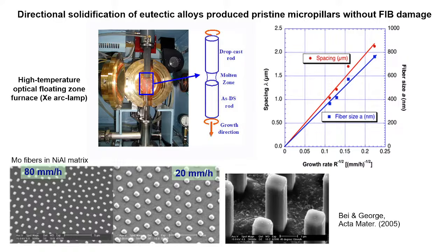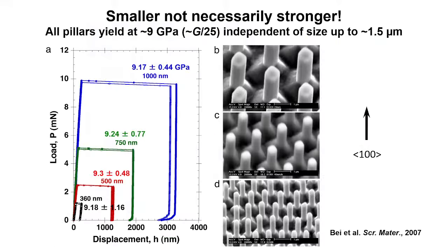And so we tested them just like UIUC did. And here's what we find, right? So we find that the stress strain curves, this is load now versus displacement. So small pillars look like this, the intermediate ones look like this. And so all the way from 360 nanometers to about one micron, right?